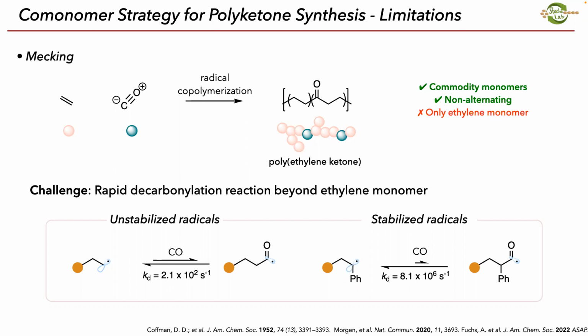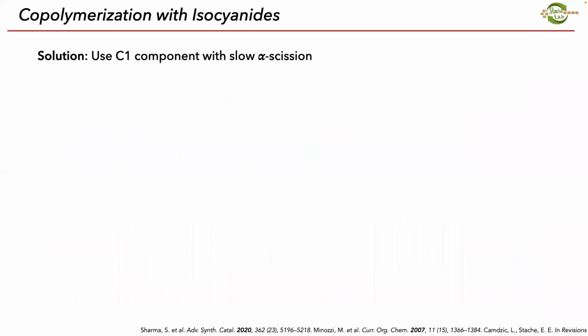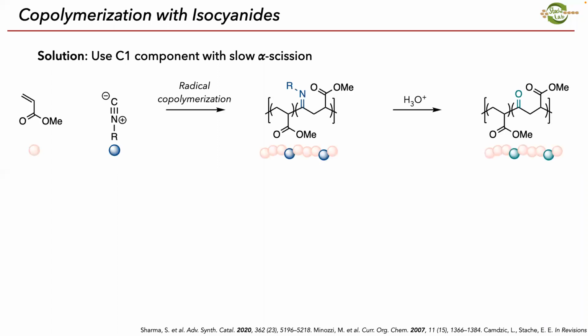But in the case of any other alkene monomer, other than ethylene, so any substituent on here, we can't drive this process forward because the reverse reaction lies to the activated stabilized radical. And so this acyl radical will rapidly decarbonylate, and so we can't incorporate CO into the backbone of these polymers. And so we looked at this problem and we thought, okay, we can't use CO to install these ketones. So instead, we're going to use a different C1 component rather than carbon monoxide that isn't going to go that reverse reaction. So we can drive the polymerization forward and install those carbonyls.